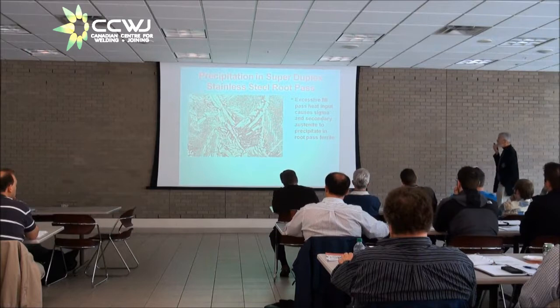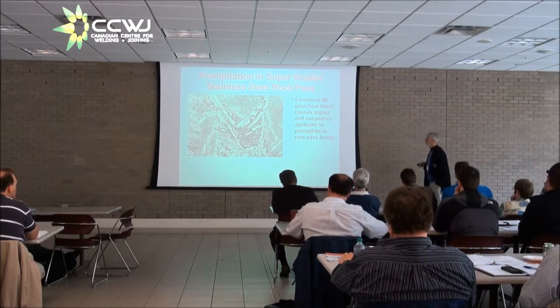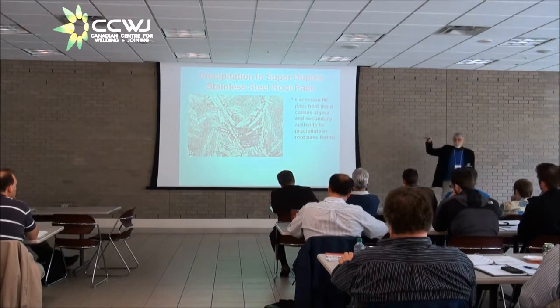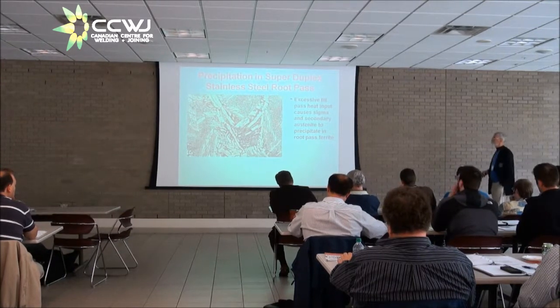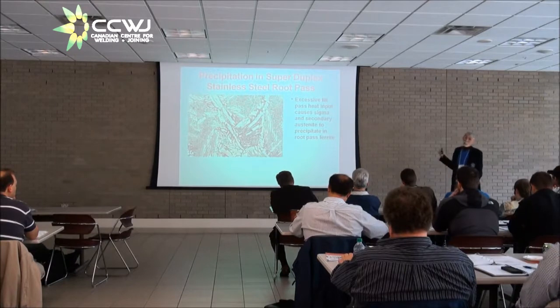This is a heat affected zone, actually, from a... I'm sorry, this is welding. This is welding. The root pass came from a customer complaint that they were failing toughness in the root area. They put in a thin root pass, followed by a hot pass. And the end result was that the